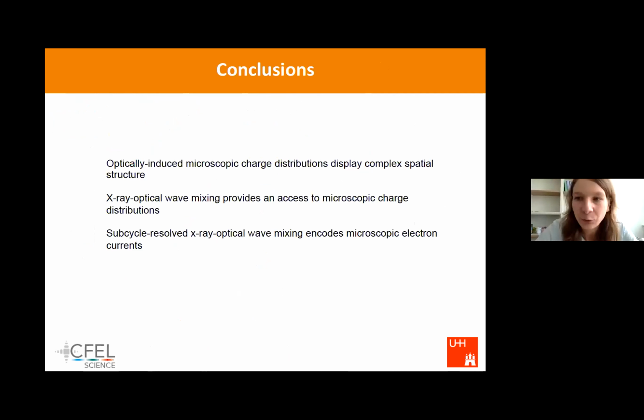So this brings me to my conclusions. First we found that on a microscopic scale, the optically induced charge distribution can have a very complex spatial structure, and we propose to image this complex spatial structure with X-rays that act simultaneously with a driving pulse. We show that this allows us to access the microscopic charge distributions. In both the time-resolved and time-unresolved cases, we get interesting insights about electron dynamics, and in the time-resolved or subcycle resolved case, we can get access to the microscopic electron currents.